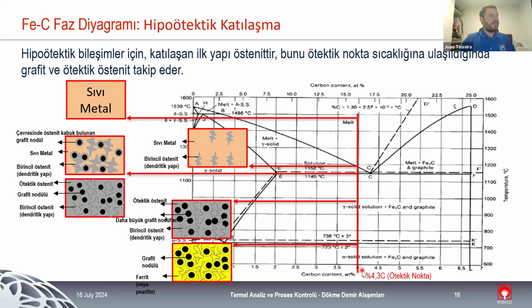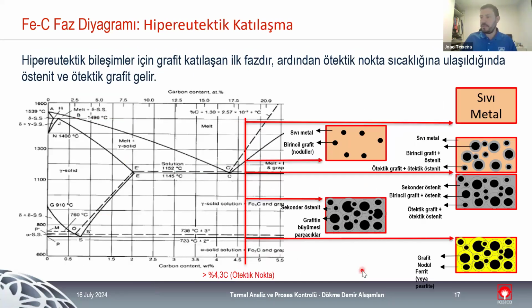And the same principle is used for hypereutectic solidification. So we have a point, we are on the right side of the eutectic point, so we have more than 4.3% carbon. And when we reach the liquidus curve, the first phase to transform is graphite, not austenite. And this is really important for a lot of different reasons. The main one is for the design of the gating system.